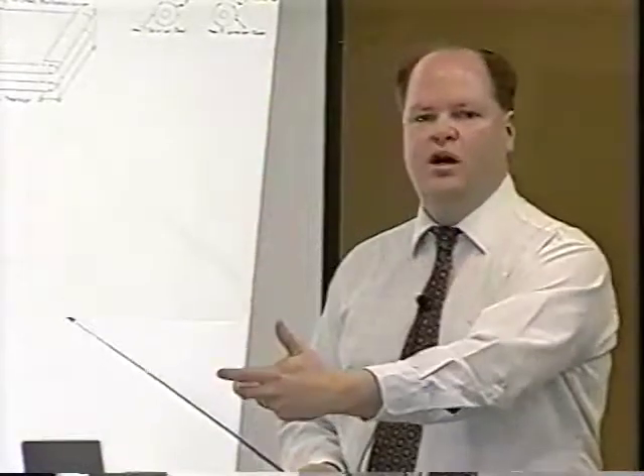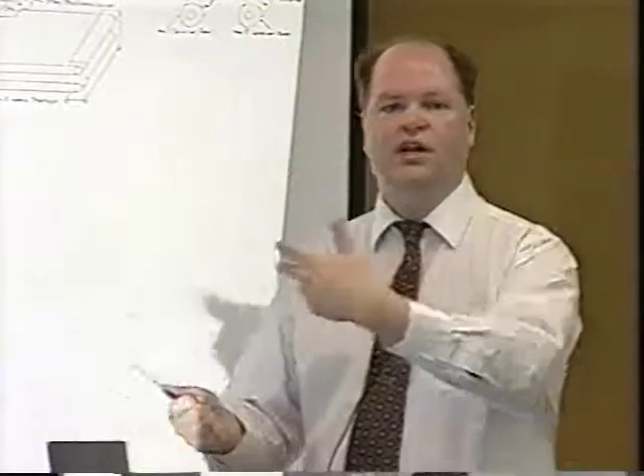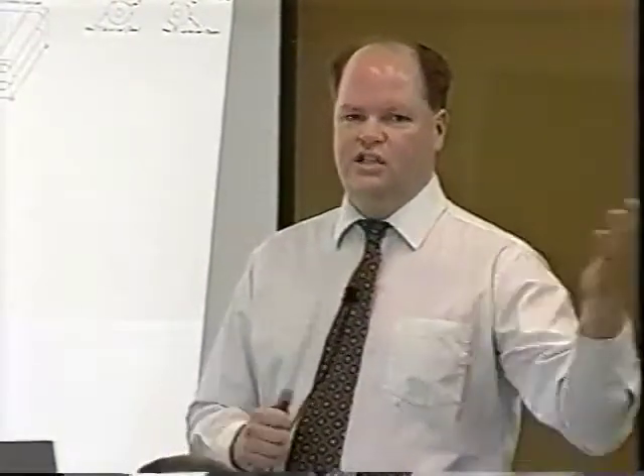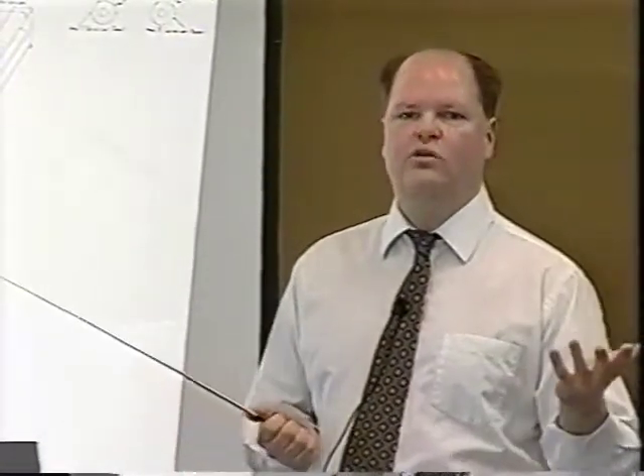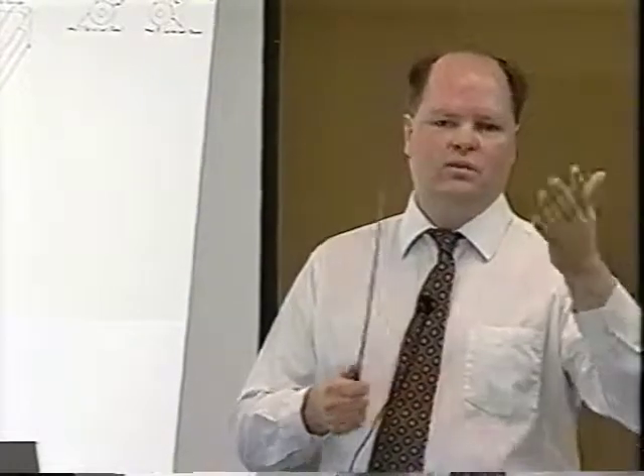Lackawanna, since they anneal offline, and they batch anneal their product, they don't have that problem. They can run any kind of gauge, and that's part of the flexibility that they have, is they batch anneal offline, and then they temper-roll it when it's done, so they don't have that strain aging returning. So that's kind of the reasoning, and it goes back to that flexibility versus efficiency, and giving us the way to go either way on it. If we only had that one line, we couldn't do it. So I don't know if that answered your question.